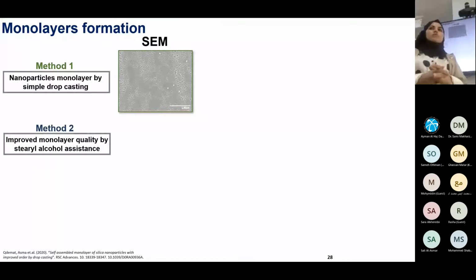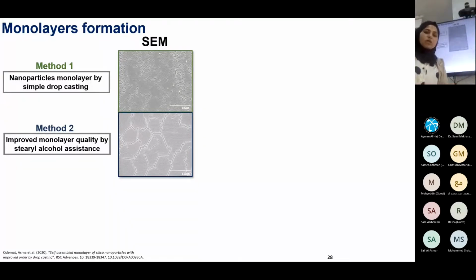In the second method, I attempted to use stearyl alcohol, and I thought this stearyl alcohol would improve the order between the nanoparticles and also fill the spaces between the cracks. Actually, we end up with a very nice ordering between the nanoparticles, better than in method one. But we end up with some domains oriented the same way, separated by cracks, which came maybe due to the drying. So in conclusion, the monolayer in method 2 is much better than the monolayer in method 1.